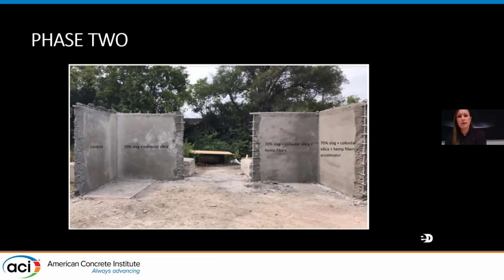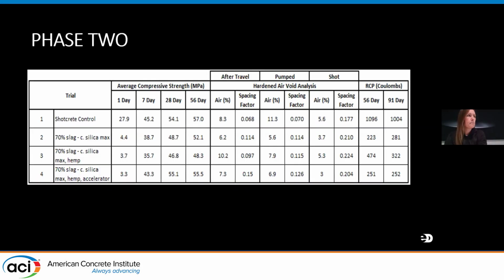And then on the other hand, the mixtures using the hemp fibers had a very, very nice finishability. The surface seemed to be enhanced due to the hemp fiber's ability to contain or capture the free water from the mix in a uniform gradient throughout the section. Again, the information on the screen represents the results from one of the trials.